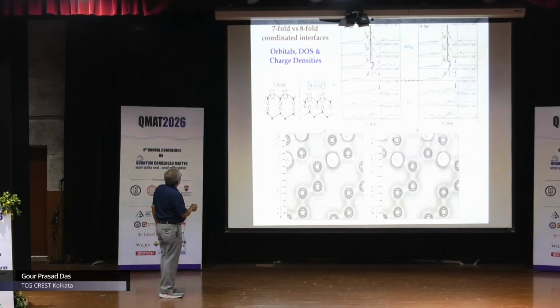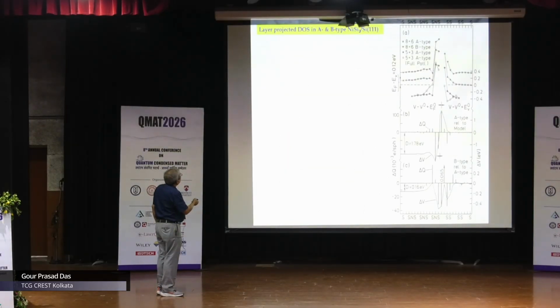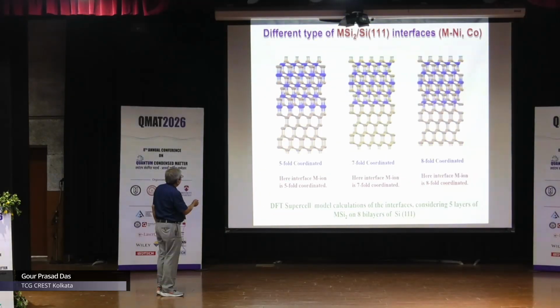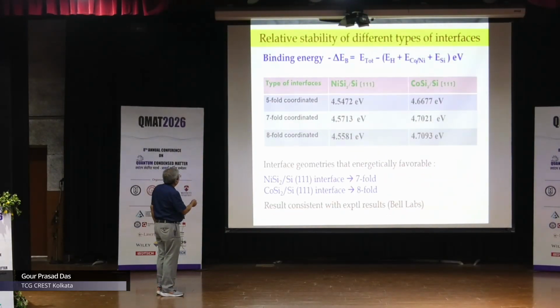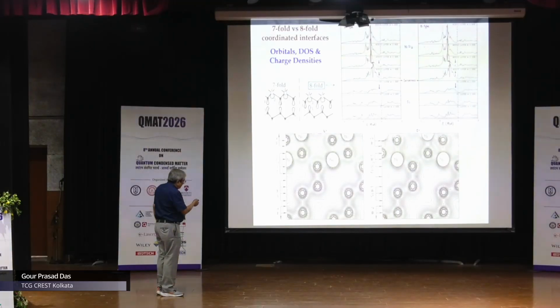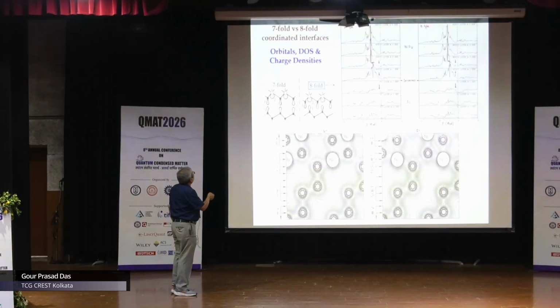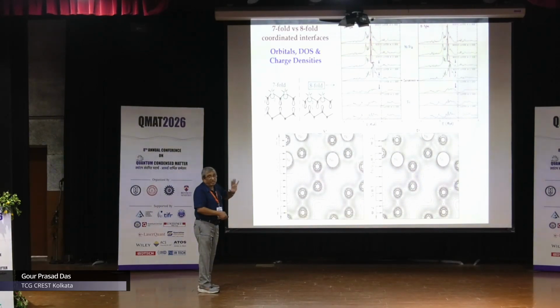I will not go into very much detail, excepting to tell you to look at how the orbitals in a 7-fold versus the 8-fold look. Can you see? Pictorially, you can see the difference between a 7-fold and an 8-fold. And interestingly, what we observe is the following. There are two different types of interfaces. Let's consider nickel disilicide silicon, which is 7-fold. We know that from experiment.